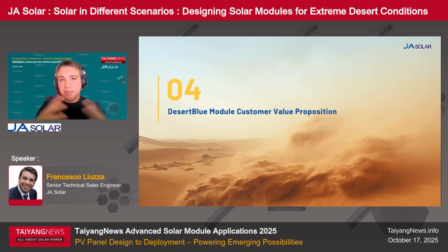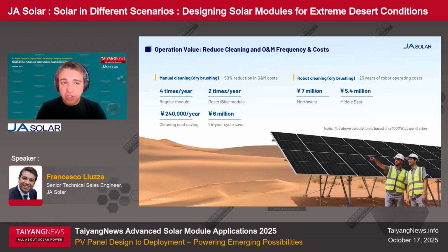But this is from the product point of view. This is translated to an operation value, something that can affect the LCOE and the BOS of a project. The manual cleaning can be reduced by about 50%. Normally it is required 4 times per year. With the DesertBlue, 2 times per year is estimated as sufficient to keep the reliability and the performance of the modules at high levels. And this can be expressed by a number calculated on a 100 megawatt power station, saving more than 6 million RMB in a 25-year cycle. And also robot cleaning reduces initial investment, and it also can reduce the cost of O&M and operational value.